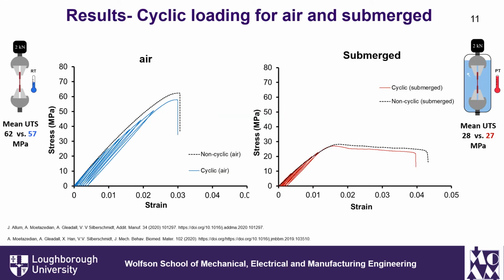In this slide we have the results for cyclic and non-cyclic plot for both air on the left hand side and submerged on the right hand side. We can identify a few differences between these two testing environments. Firstly, the mean ultimate tensile strength reduced by 5 megapascal from 62 to 57 megapascal, as well as we observing some cyclic softening for air specimens. On the other hand, for submerged testing, the reduction was negligible, as well as the cyclic curve followed the master curve, and this may have happened due to the differences between tensile environment.